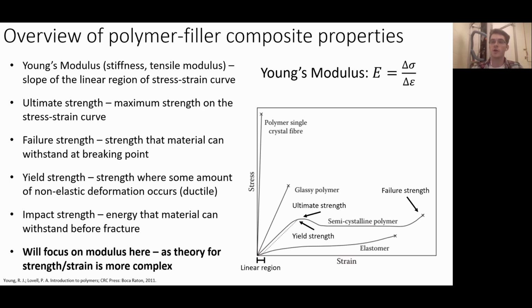We have our yield strength, which is some strength at a set amount of deformation past our elastic region. We have our ultimate strength, which is basically the peak of that stress strain curve for a ductile polymer. And we have our failure strength, which is where the material fractures. So some of these values can actually be the same depending on what polymer you're looking at. For example, for a polymer single crystal fiber, all we have is a failure strength. And so there would be no ultimate strength in this case, or they would all be the same.